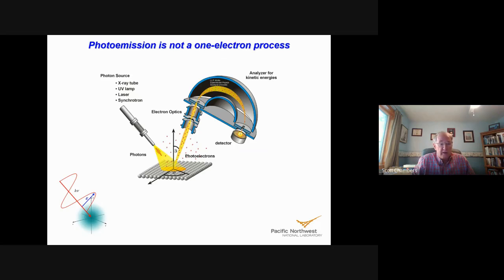We see an atomic orbital on an atom, it absorbs an X-ray, and out comes an electron. And then the way that conservation of energy relationship is usually expressed, which is a very useful formula, this one, which relates the X-ray energy to the measured kinetic energy of the outgoing photoelectron, and then its binding energy in the solid, and there's a correction for the work function of the analyzer. But that equation really leads to a one-electron paradigm. You'd have one orbital on one atom, you send in one X-ray, and out comes one electron. Boom. But that's not really what happens physically.